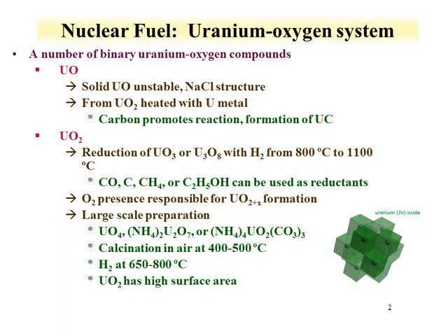More dominant species is uranium dioxide. This can be formed by the reduction of a number of oxides, as shown here. Hydrogen can be used as a reductant. In our lab, we use 5% hydrogen in argon as a common route for producing UO2. These other compounds can also be used as reductants.